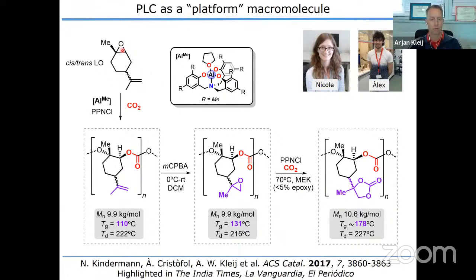Of course, we can make use of polylimonene carbonate itself as a platform molecule. We're not the only ones that have worked in this field, but we have looked at several functionalizations using thiol-ene chemistry, but also other types of addition reactions, making changes in the hydrophobic and hydrophilic nature. I'm not going into that in too much detail. I'd like to show you one particular example where we can do oxidation on the polymer. We are oxidizing that double bond, getting an epoxy group, which is by itself really interesting to consider as a platform molecule. By incorporating a second CO2 molecule in the repeat unit, we can even make a cyclic carbonate that also has quite modular reactivity in terms of ring-opening chemistry. So we believe that we now have made a nice series of platform molecules that we can valorize towards functional polymer-based applications. And this is what we are doing right now.